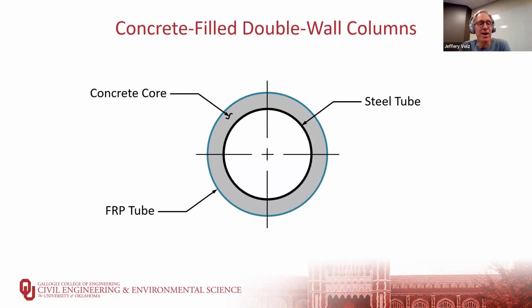The idea is that if you take a ball of concrete and drop it into the deepest part of the ocean, it will never fail in compression because it's under a high hydrostatic pressure in compression. And so it really can't fail. And you can get astronomically high compressive stresses. That's the same application here where the inner steel tube and the outer FRP tube provide confinement to the concrete. So it has a much higher apparent strength than its uniaxial compressive strength.